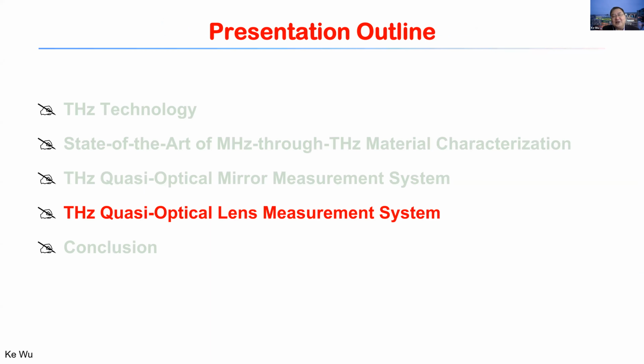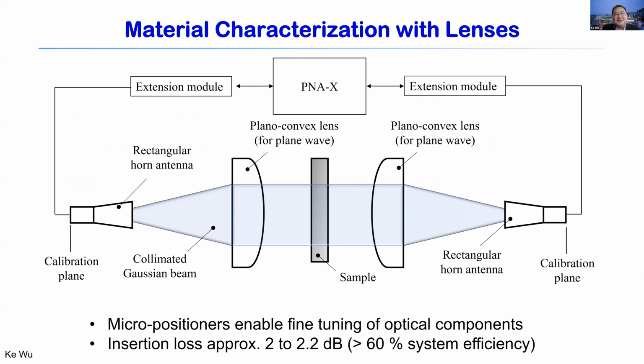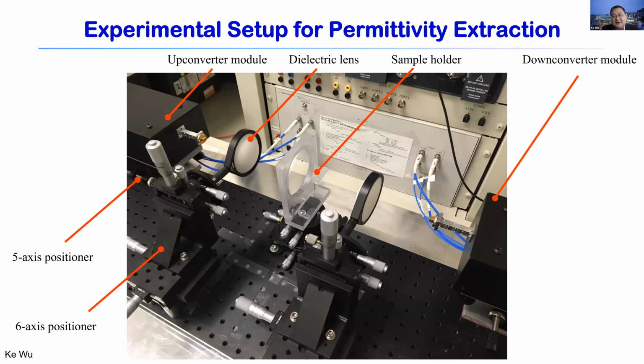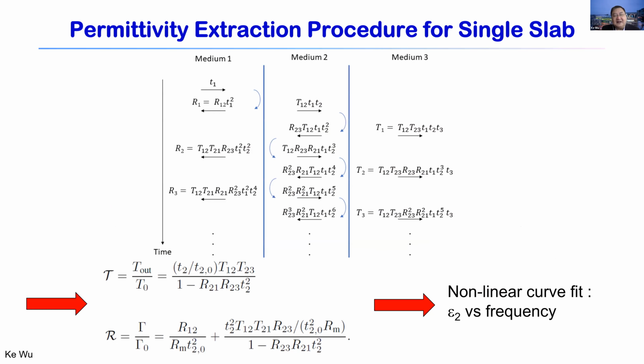So let me go quickly through the quasi-optical lens measurement system because of time. We also developed the lens measurement system using Gaussian beams. The Gaussian beam here uses a rectangular horn antenna. Of course, here it is an approximate Gaussian beam, but we can get pretty good values because this planar convex lens gives us a very good conversion from the Gaussian beam to planar waves. This is a measurement setup we developed for the D band, and also the G band. I will not go through this.